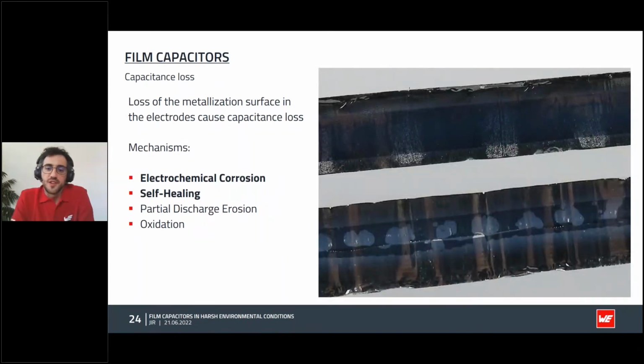There is also self-healing damage, which will appear when the capacitor is absorbing damage created by a surge voltage process, and the discharge arc will cause the vaporization of the dielectric and metallization. After the arc, the insulation is restored, but an area of metallization is lost. You can see the corrosion damage in the top image, as well as the self-healing damage in the bottom image. The very white spots are where the arc happened, or in this case, many arcs. Partial discharge and oxidation processes can also have an impact, but it is smaller and greatly reduced by the plastic casing and hermetic sealing of the film capacitors.